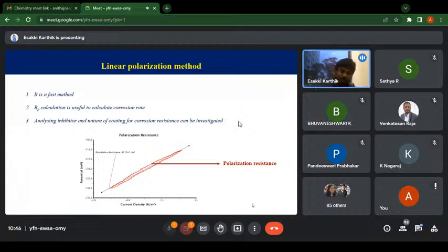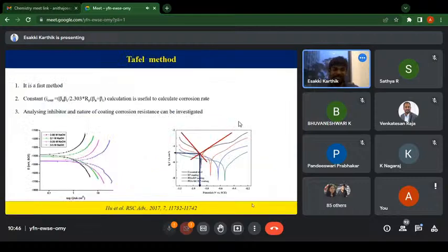From the slope of this graph, you can find out the polarization resistance, RP. When you know the RP, this RP will tell about the rate of the corrosion current. RP is the corrosion resistance. When you invert it, that is the corrosion current. Once you know the RP, after that you have to do the Tafel method. You have to run the Tafel analysis.